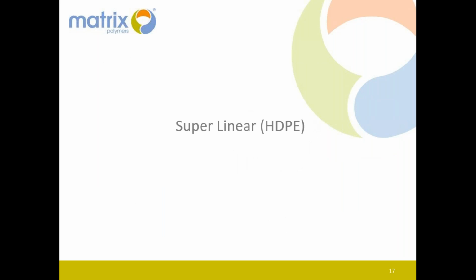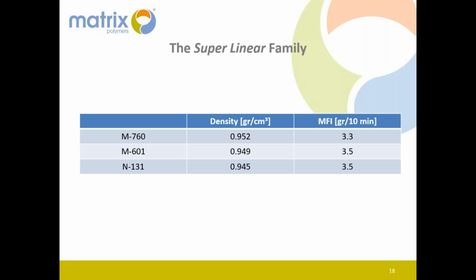Now, this range of materials called Superlinear are essentially very high density materials. These are available commercially, and we need to see where the applications are that they can be used at. You can see that the densities range from 0.945 to 0.952. MFI is relatively low, kept low, so that ensures the toughness and mechanical properties are good, as well as the stiffness and the other features of the higher density are availed in these materials.